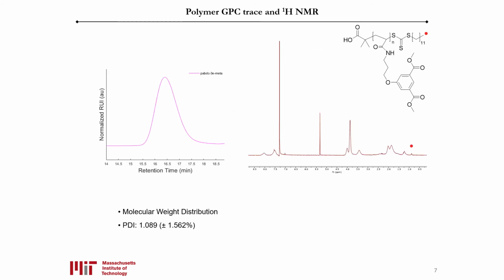After the kinetics experiment was completed, a gel permeation chromatography trace and a hydrogen NMR was taken. The GPC shows a unimodal curve which indicates a uniform molecular weight distribution among the polymer, and the polydispersity index, or PDI, was calculated to have a low dispersity.